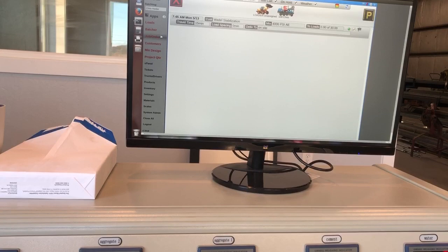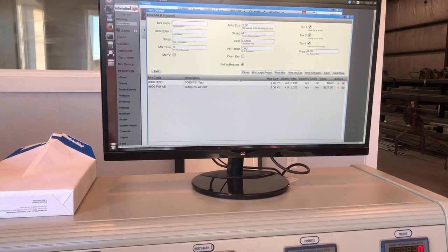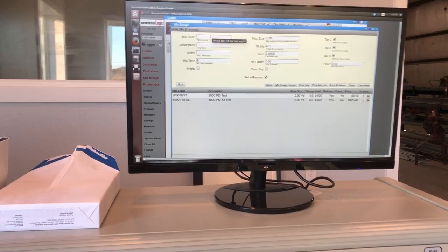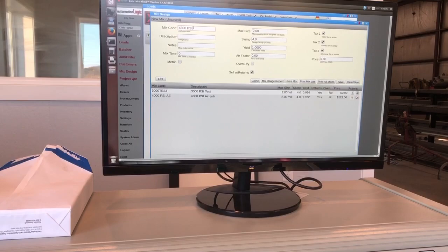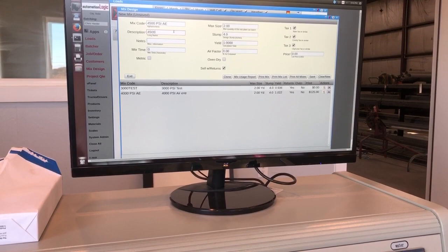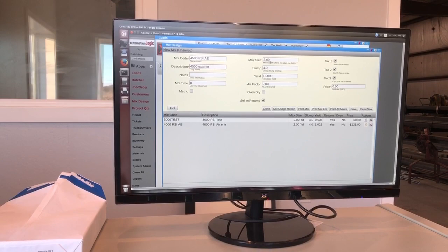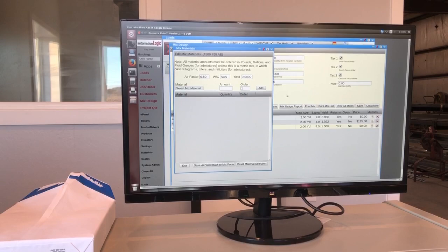The other thing is mix design. Right now we have, we've been pouring this 4,000 PSI air entrained. To make a new mix design, all I would need to do is click clear new. Then I'd start typing my mix code. So let's just say I was going to do a 4,500. I type 4,500, maybe I'm going to call it PSI with air, AE for air entrained. And then I can have another name for it, which would be maybe like 4,500 exterior. Max size this plant can batch, it's a two yard twin shaft, so it's two yards. Slump, and we're going to design it to a four slump. Yield air factors here entrained at 6.5% air. And when I do that now, I'm going to hit save, it populates up this screen.